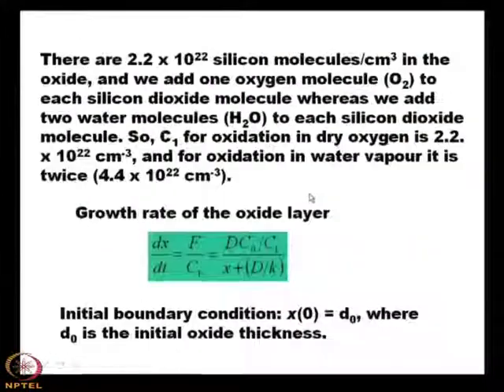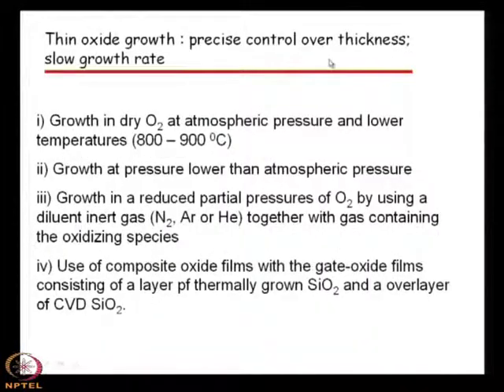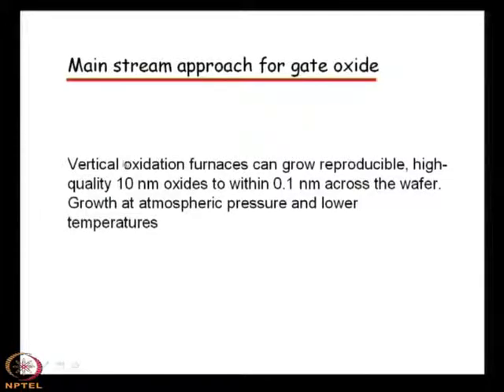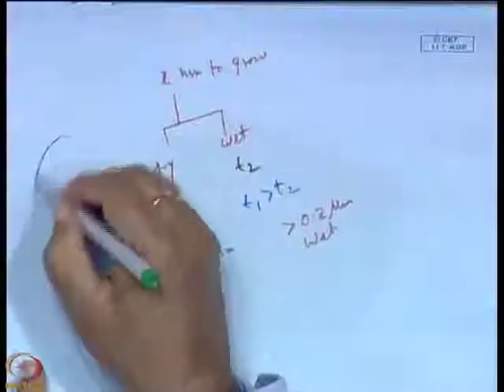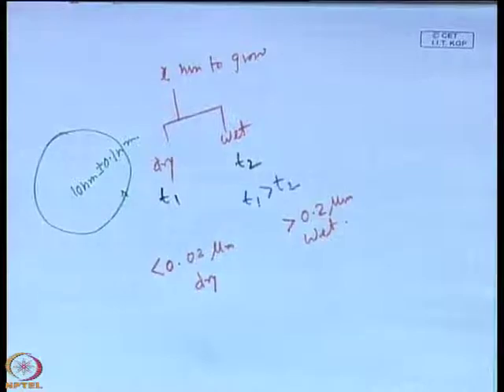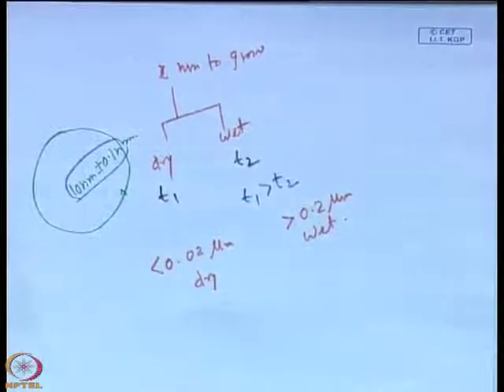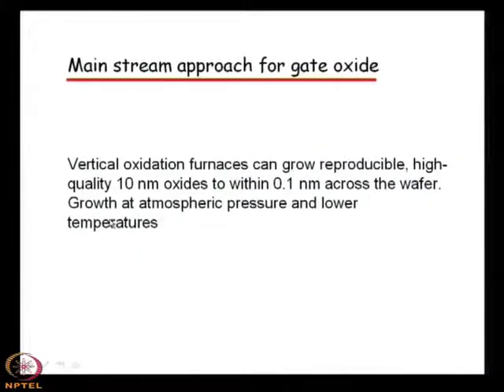So, what we see is that the oxides grown in the furnace, which can be a vertical one, can be reproducible and high quality. A vertical oxidation furnace can grow 10 nanometer oxides to within 0.1 nanometer across the wafer. So, if you have a wafer of, say, 6 inch, the oxide layers can be 10 nanometer plus or minus 0.1 nanometer. That is very precise, and this 10 nanometer is what is used as the gate oxide in MOS technology, grown at atmospheric pressure and at lower temperatures. That is the mainstream approach for gate oxide in the industry.